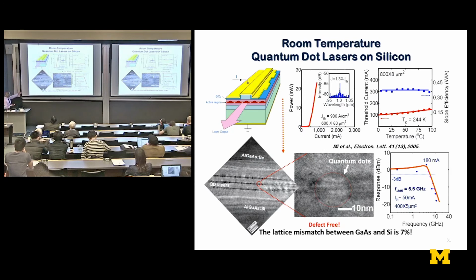And we did another thing. We used these quantum dots in the buffer layer itself. These quantum dots act as filters to trap dislocations, and they work very effectively as dislocation filters. So we used quantum dots not just in the gain region, but also in the buffer region.